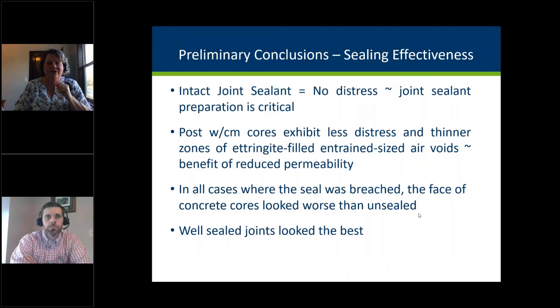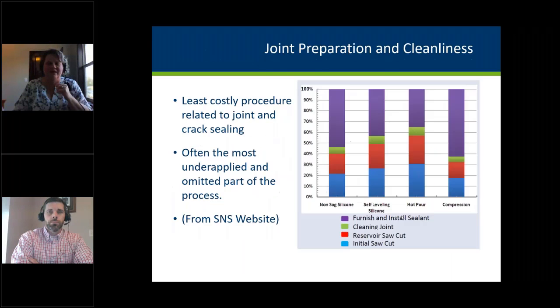So what were our preliminary conclusions on the effectiveness? When that seal is in good shape, everything is great. We saw the post-water cement cores exhibited less distress than the pre-water cement cores. In all cases where the seal was breached, the face of the cores looked worse than unsealed. And like I said, well sealed looked the best.